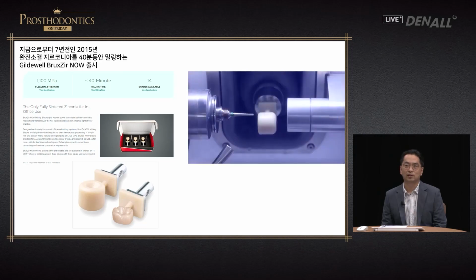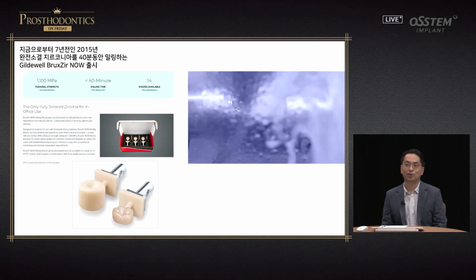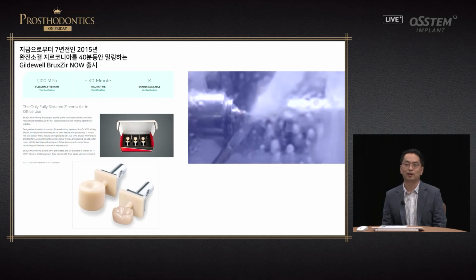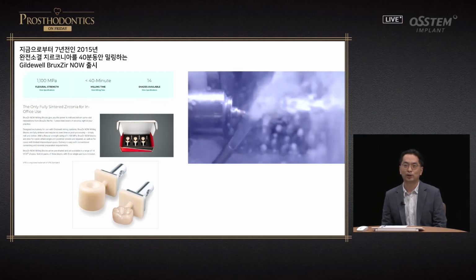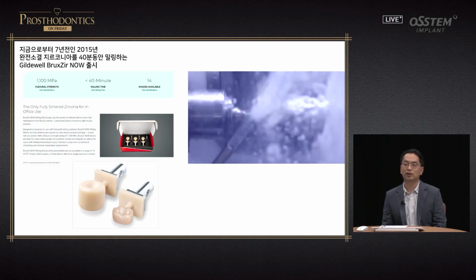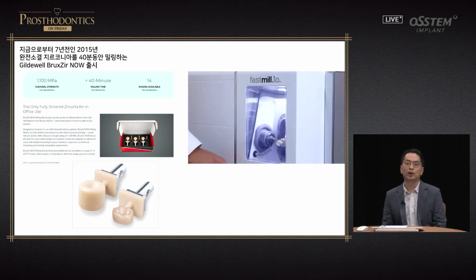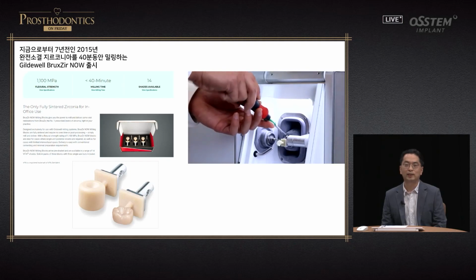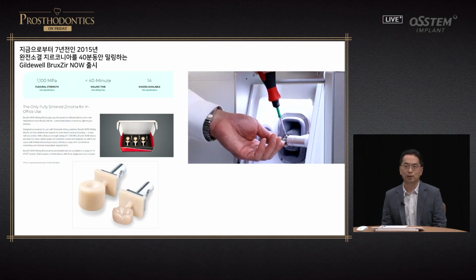Glidewell of the USA in 2015 released BruxZir NOW. I'm sure you have prepped a zirconia crown. In my dental clinic, you would have to use 2 or 3 very rough diamond burrs to prep it. Fabrication is possible, and fabrication within 40 minutes is possible. I've never used this product, but in order to fabricate this zirconia crown, I think a significant use of burrs may be required.